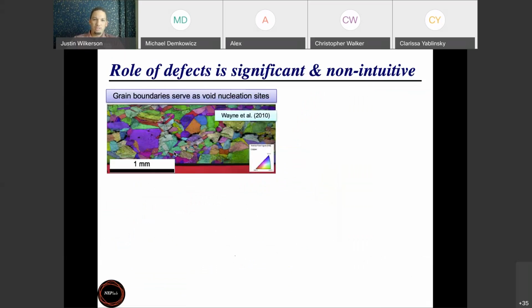So one thing I'll show here is that grain boundaries tend to serve as void nucleation sites in spall failure. So you can see these. This is an EBSD image, so every color is a grain oriented in a different way, and the boundary between two different colors is a grain boundary. And so these black regions here are showing voids and damage that's nucleating primarily along grain boundaries. There are some voids nucleating in the interiors of large grains, but for the most part, it's mostly along grain